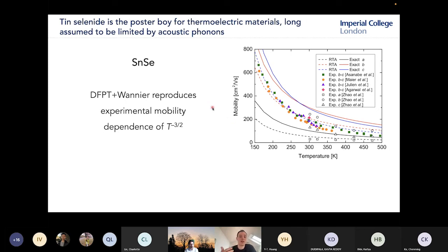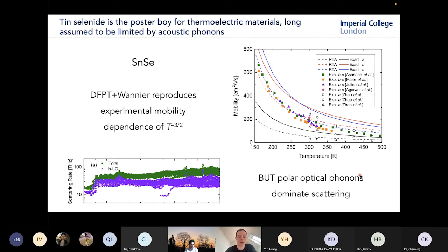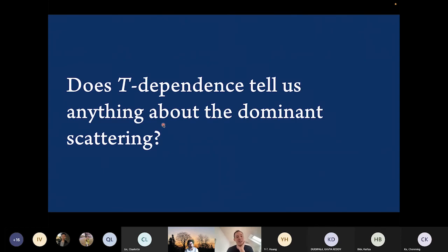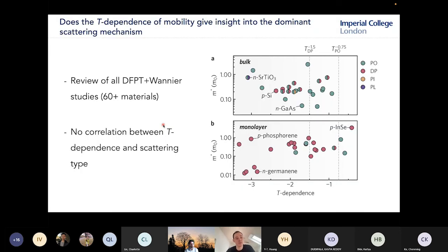But when people ran DFPT plus Wannier on this material, they found that their calculations reproduce the experimental temperature dependence very well. But when they actually looked at the scattering physics, they found that polar optical phonons dominated the scattering, not acoustic phonon scattering, as had been presumed based on this temperature dependence. This really raised the question, I think, does this temperature dependence of mobility actually tell us anything about the dominant scattering mechanism? That's what I wanted to look into with this work. To start with, I did a review of all DFPT plus Wannier calculations to date.